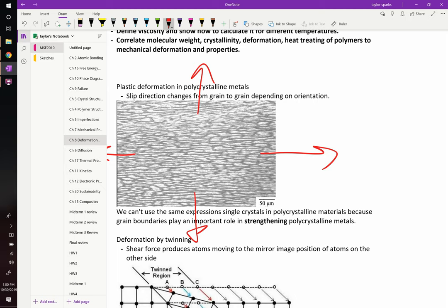Now, do you think this is going to be an isotropic material? Yeah, no way. How come? Well, part of the way that things deform is grains sliding past one another. Another way is, remember that each one of these has dislocations maybe inside of it, and the degree to which that dislocation can move through the grain tells you how ductile it's going to be. So you might expect it to have better ductility traveling left and right,